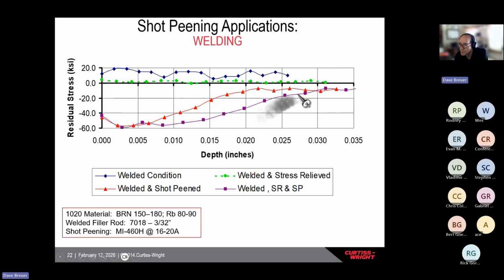So let's look at this purple curve here. This metal is much softer than a typical spring wire, so you'll see the peak residual stress is about 60 KSI. And if we look at the depth, this might be 25 thousandths deep here.